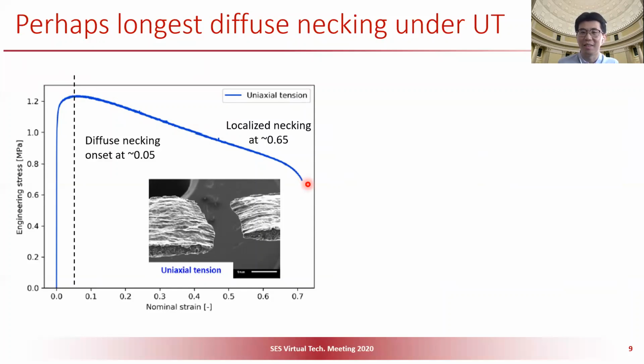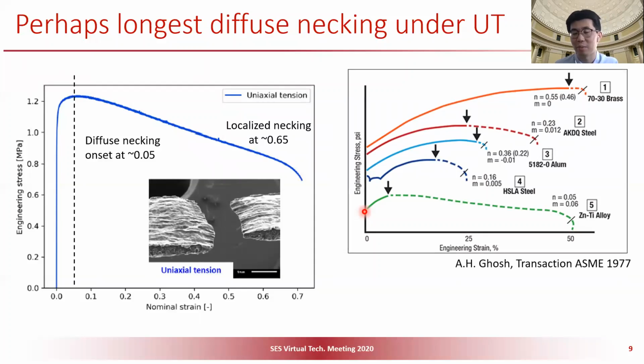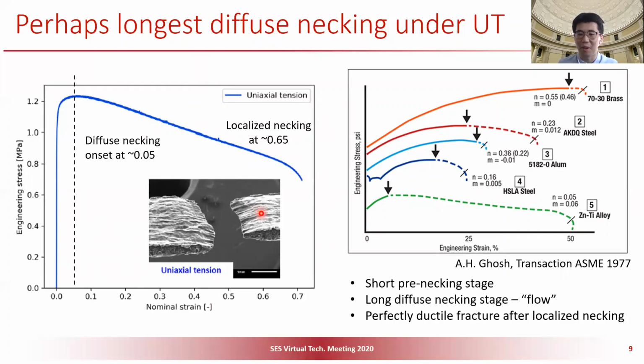So lithium metal is really interesting in terms of mechanical behavior. To roughly give you an idea, I put 5 other materials here for you to compare. There are brass, steels, and different steel aluminum, and none of them behaves like pure lithium. Of course, there is one material, a zinc titanium alloy. It's really soft, like our lithium. However, lithium is the only one with such a short pre-necking stage and such a long diffuse necking stage. So that means the material starts to flow.